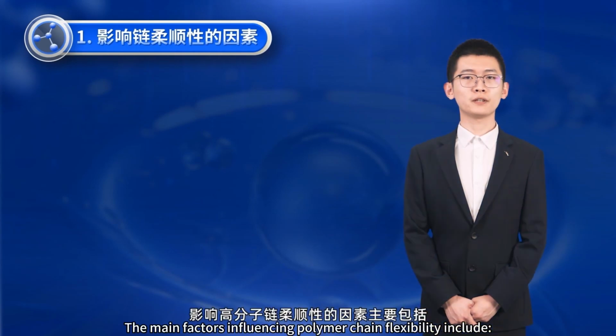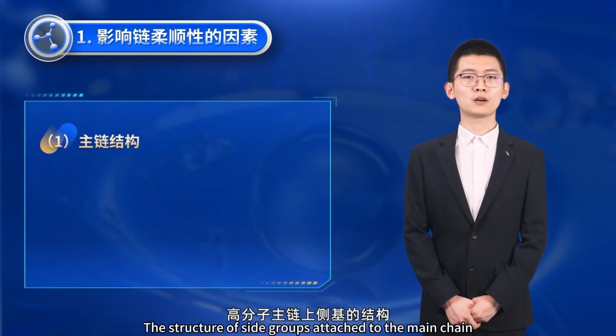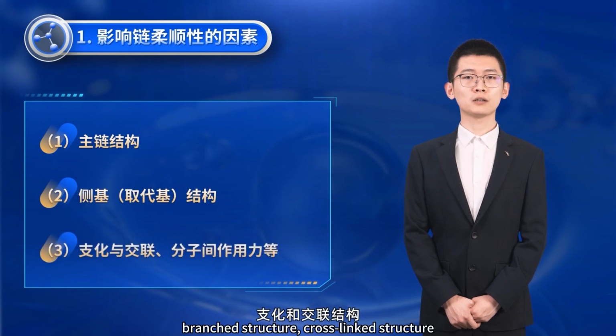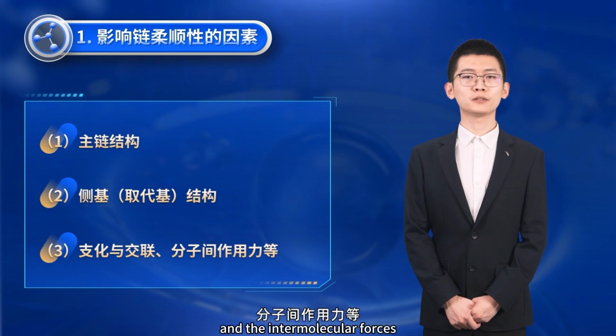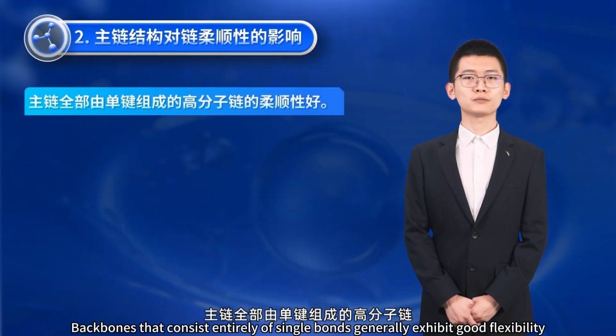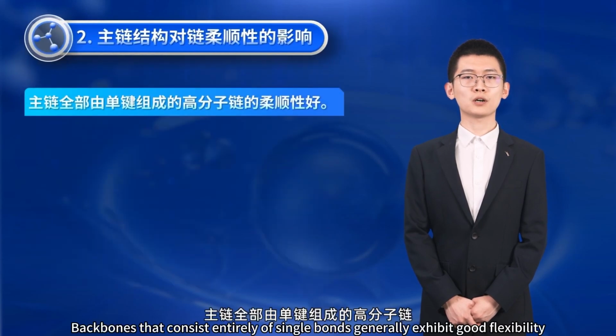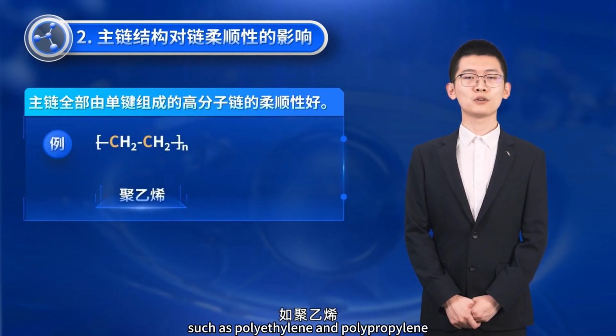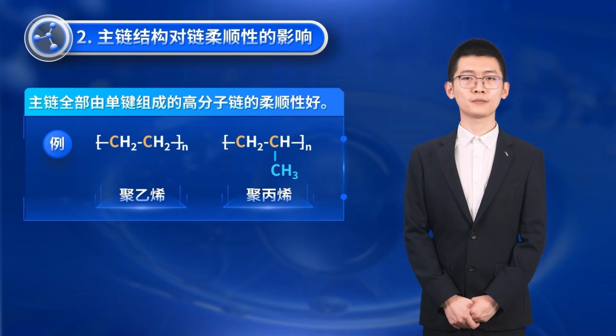The main factors influencing polymer chain flexibility include the structure of the polymer backbone, the structure of side groups attached to the main chain, branched structure, cross-linked structure, and the intermolecular forces. Backbones that consist entirely of single bonds generally exhibit good flexibility, such as polyethylene and polypropylene.